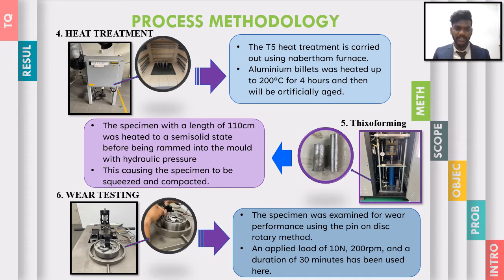And after the heat treatment, we are supposed to do the THIXOFORMING. So the THIXOFORMING was done using 110 centimeter specimens. The specimens were first heated up to the semi-solid stage, and then rammed using a hydraulic rammer with an approximate pressure or load of 10 kilonewton. From that, the specimen was rammed and also reduced in shape. The rammed and compacted specimen was then sent again for microstructure and also to evaluate the wear performance, in order to characterize and justify the quality enhancements.